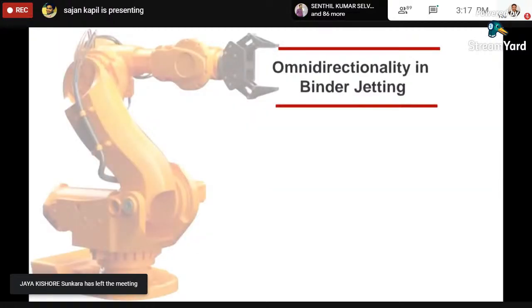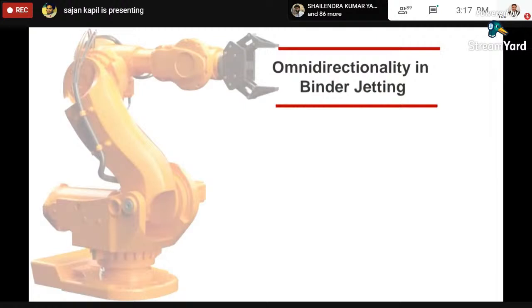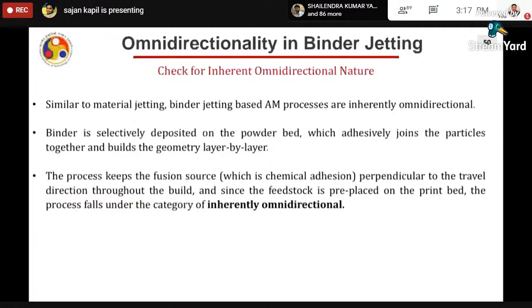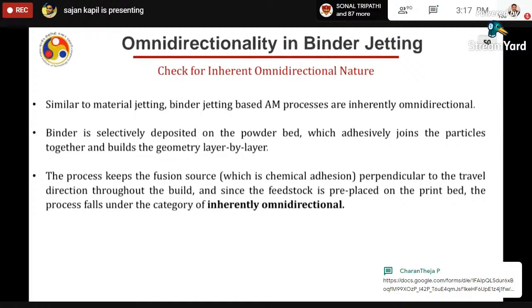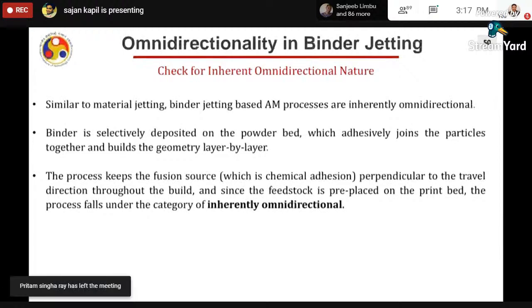Omnidirectionality in binder jetting. Binder jetting means, in this case, on the substrate you have powder, and from the top the binder will come. Similar to material jetting, binder jetting based processes are also inherently omnidirectional because binder is selectively deposited on the powder bed, which adhesively joins the particles together with the build geometry layer by layer.